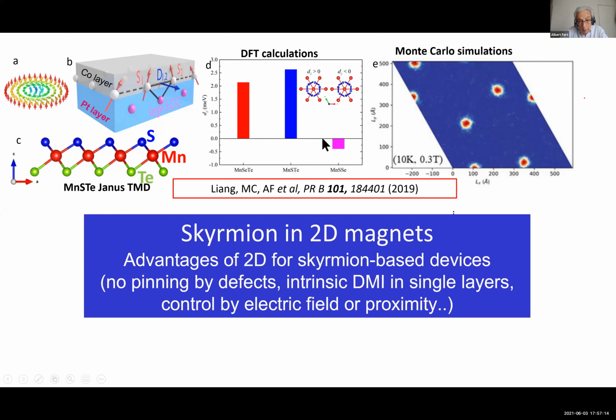And also, going on with Monte Carlo simulation using the exchange and DMI parameters found for these monolayers of TMD, one finds that the ground states at some field, at least, are chiral structures, skyrmions. This is a type of relatively small skyrmion that can be predicted in this TMD. So this is a principle: find 2D materials with this intrinsic breaking of symmetry. It's not the only way to have the Dzyaloshinskii-Moriya interaction and skyrmions. In fact, it can be done also in the usual way by introducing an interface, like with 3D material, cobalt-platinum, for example. And this corresponds to the next result that I show.